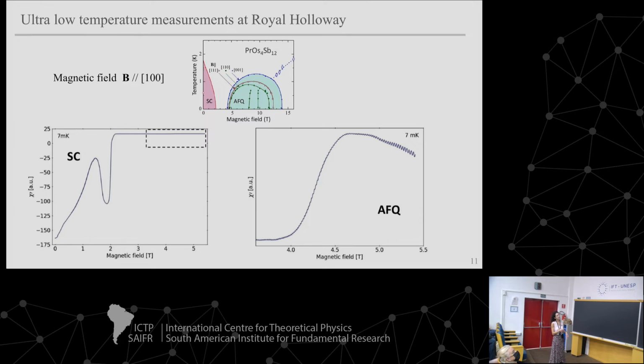So this is up here, and you can see not only that there's a very sharp and prominent transition into the antiferroquadrupole phase, but you can see, I hope, that the quantum oscillations are there on top of this. And the quantum oscillations continue all the way through the phase transition, so the width of the phase transition is not smearing or inhomogeneity in the material, it's an intrinsic width of this transition. If it were smearing or some kind of inhomogeneity, then the quantum oscillations would also be damped across the transition. You wouldn't see them. The fact that they don't change all the way through tells us that it's an intrinsic width.